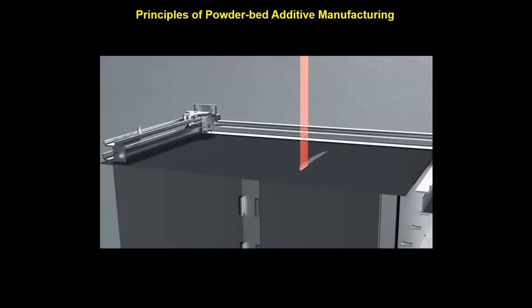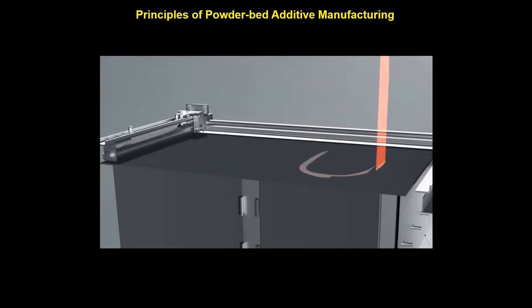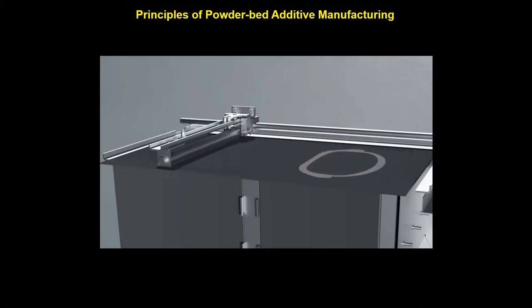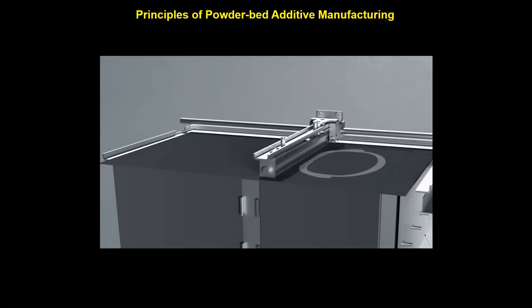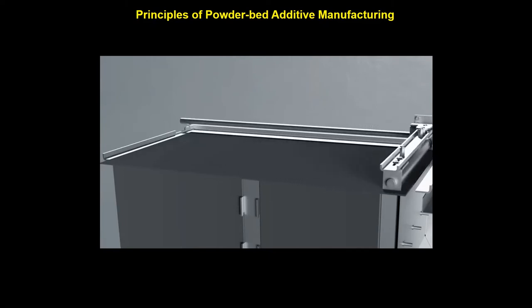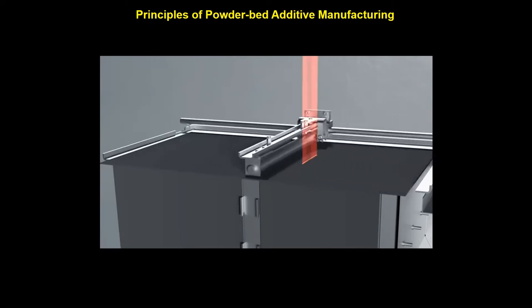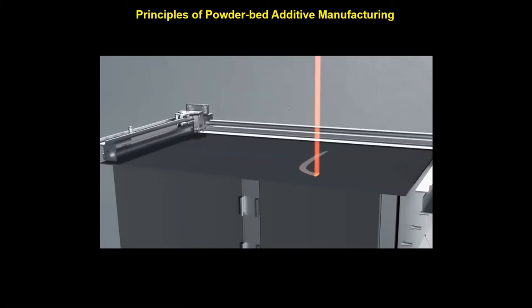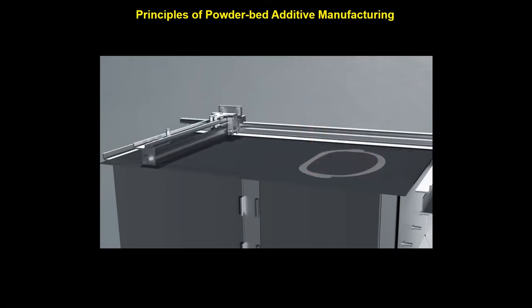The technique I used in my research is the laser powder bed or selective laser melting technology. Initially, a layer of powder material is deposited on the building plate, then the laser beam moves across the surface and melts the powder material at the specified regions based on the CAD model we already designed. Then the building plate moves downward and the fresh layer of powder is deposited, and this procedure repeats again and again until the complete part is produced.